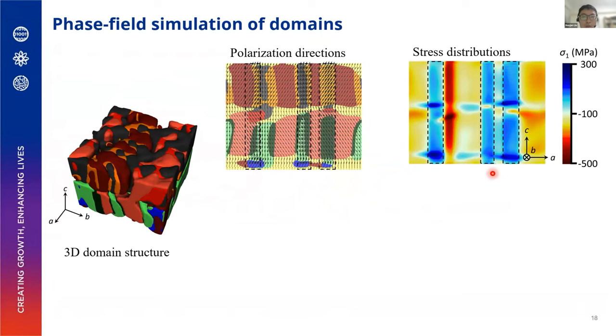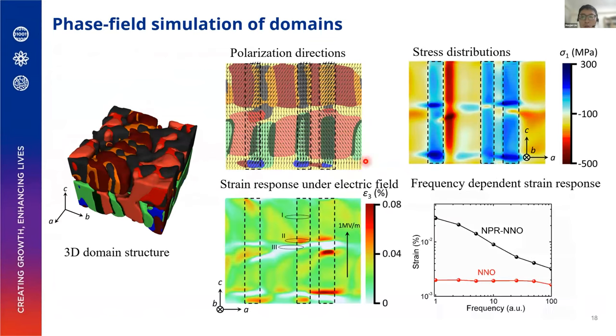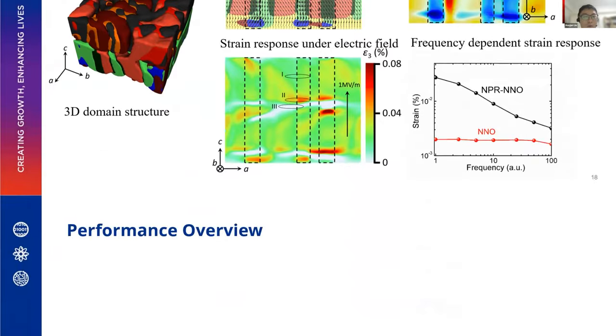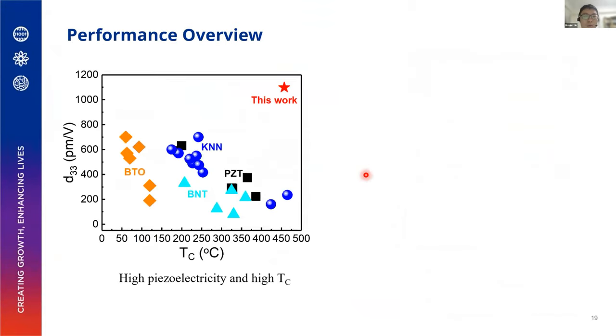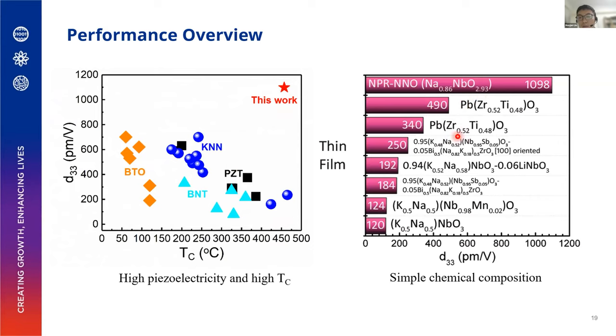And then we also have the phase field simulation to help us understand the boundary contribution. So the area at the boundary between the pillars and the matrix actually shows a stronger strain response to the electric field. Okay, then if we look at the performance of this film compared with other material systems, we are able to achieve a much higher piezoelectric coefficient, and at the same time we maintain the Curie temperature. Okay, then if we compare with other thin films, we have simpler compositions. So that's also an advantage.